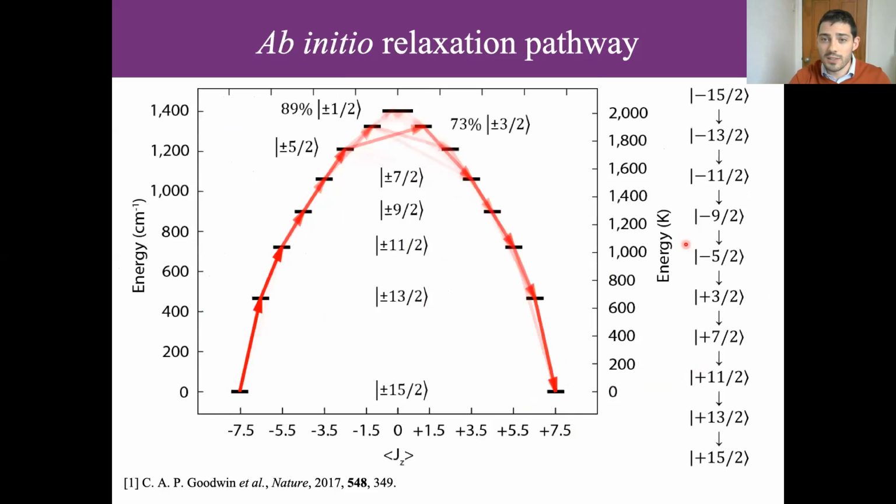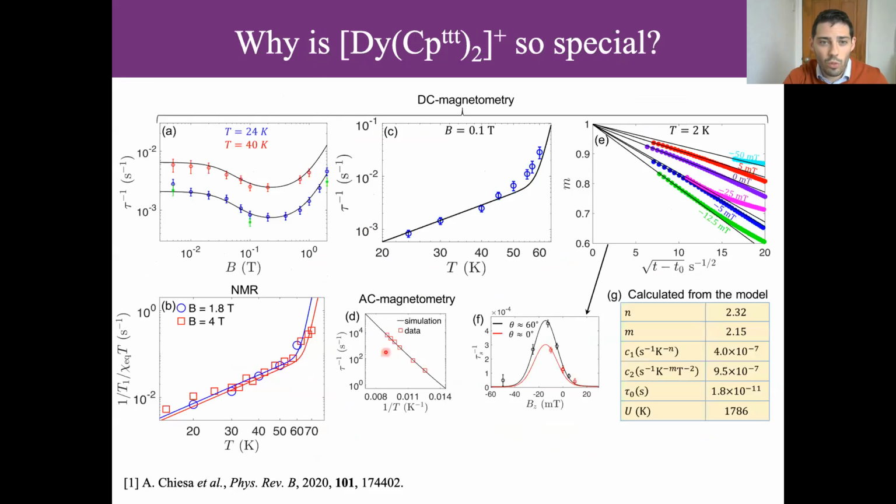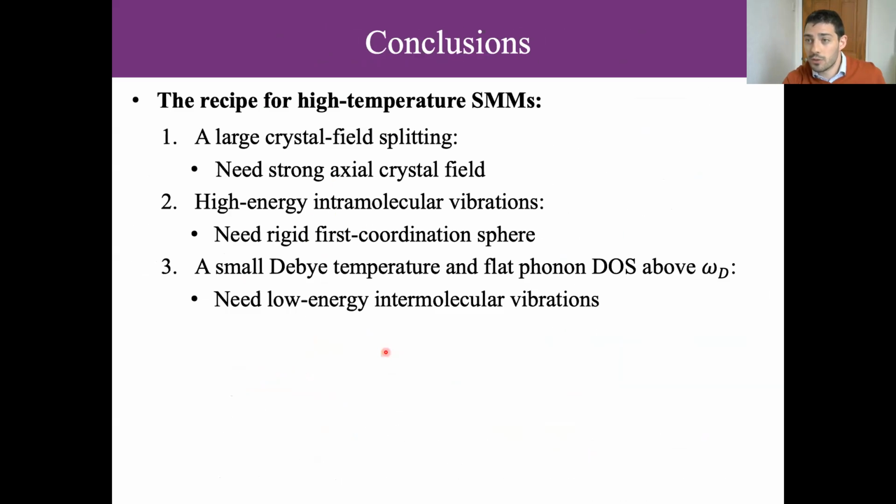And the counterion here is massive, very weakly coordinating, and covered in fluorine. So essentially you have very weak interactions. These are electrostatic, a negative charge and a positive charge, but that's basically it. You maybe have dispersion forces, but we don't have hydrogen bonding, we don't have pi-pi stacking, we don't have small molecules that can interlock very nicely. These just pack like big balls. They don't really tessellate very well. So that all helps, and having weak intermolecular interactions is a good thing.